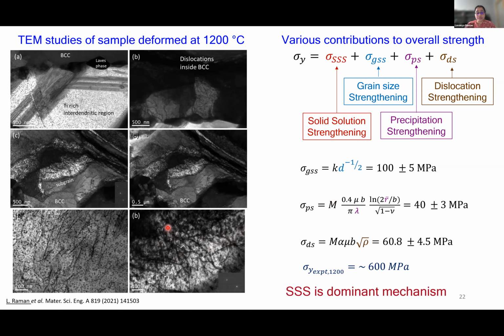So basically, from the TEM images shown in the last two figures, I was able to calculate the dislocation length, the number of dislocations in a given area. From multiple images, I calculated the dislocation density, and using this formula we can get the strength from the dislocations. How about if the dislocations are really tangled, like in the right-hand side images? How do you estimate the length?